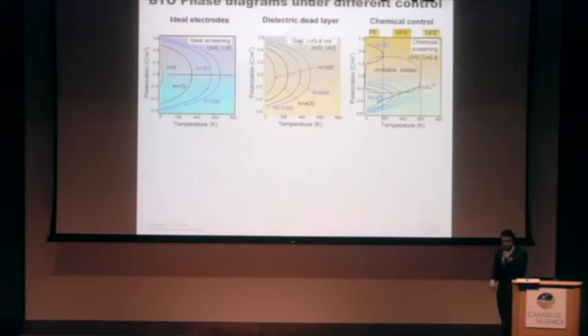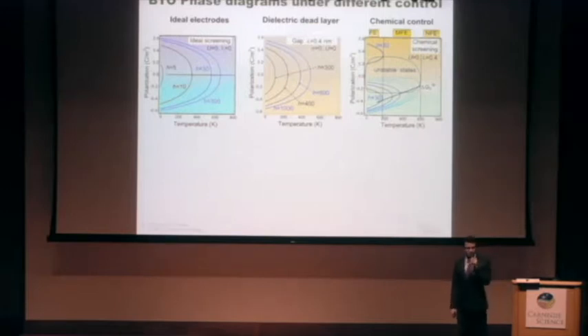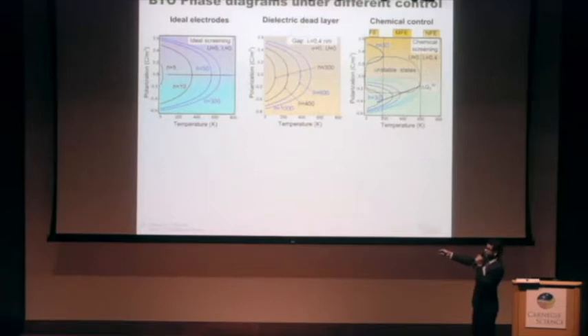So Anna went ahead and calculated what it should look like for barium titanate under different thicknesses. In this case, you can see the phase diagram for barium titanate under ideal screening. This is the general case, which everybody already knows. At high temperatures, of course, you see that it's paraelectric, there's no polarization.